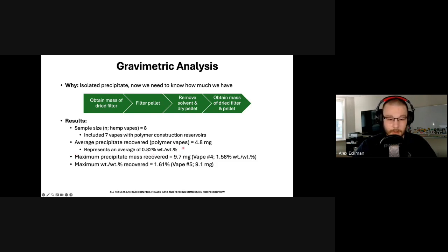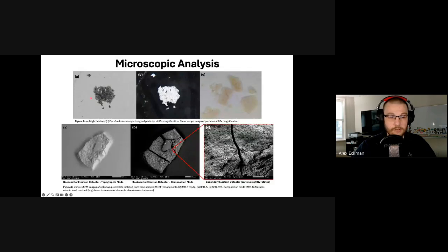0.82%. The maximum precipitant recovered was from vape number 4. That was 9.7 milligrams, representing a 1.58% weight by weight percent basis. And then when we look at which one was the worst on a weight by weight percent basis, that was actually going to be vape number 5, where 1.61% of the distillate that we took out of the vape actually contained this unknown precipitant. So that was certainly a cause for alarm.